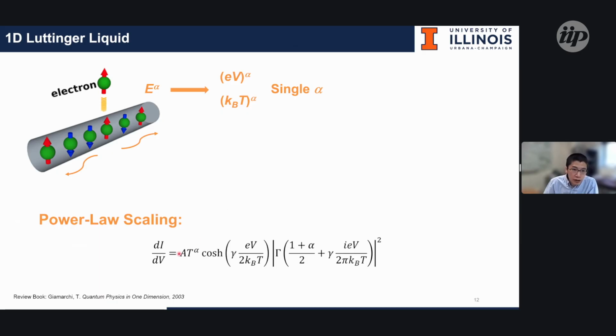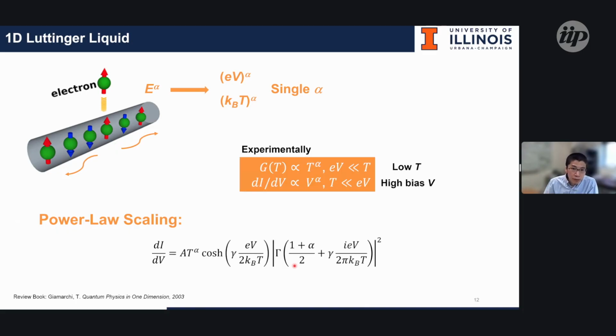For this power law, in carbon nanotubes, people simplify it into an equation that has a power law of temperature, as well as a power law of external bias in the second term. Experimentally, if we look into the system, at a very low energy excitation range, the temperature dependence should follow the power law on the conductivity. But at very high energy excitation, the power law should follow the external bias.